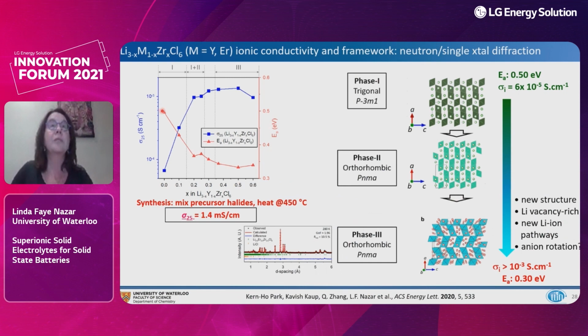And this is a so-called trigonal phase with this space group. And as we start to substitute zirconium into the lattice, we move into a region where we have a mixture of phase 1 and this phase 2. And then finally, in region 3, we switch to a completely different phase. And this, though it has the same space group as this other material, is completely different. And you can see that just from the diagrams that I've drawn. So this is a new structure. It is fundamentally different than the others.